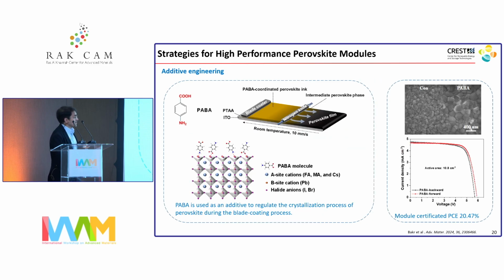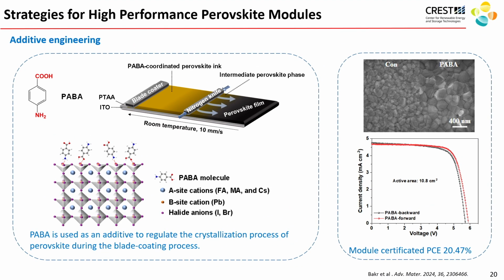There's also big challenges in terms of fabrication of the device. At the moment, all the champion devices that are being produced are made through a method called spin coating. And spin coating is a process that allows you to make small devices, but it's not really scalable to larger area fabrication. And for perovskites to be commercially viable, we have to develop ways that make its manufacturability simple. One area is blade coating, but what people are finding out is that the crystallization kinetics in blade coating is very different. And so the processing of these devices requires some different modeling and different ways of looking at it than simple spin coating.